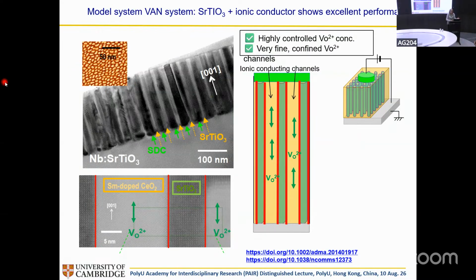It's like a butterfly wing structure, but at a much finer scale, because the butterfly wing's a micron sort of structure. This is nanometer. And we can look at these lovely epitaxial materials. So we've got an ionic conductor with an interface that's conducting, formed by mismatch of the structures, with the strontium titanate as the matrix. So it's quite complex.